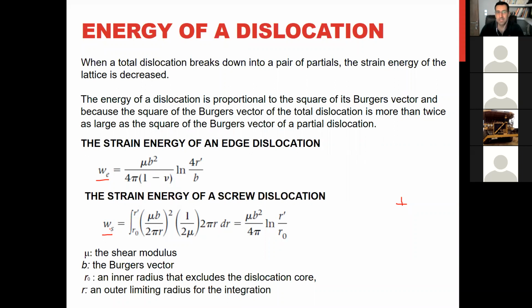I'm not going into details of how we can calculate. You can find it in the reference books I presented. So you can see the details, but something very important for us, and easy to use, is that the energy of the dislocation is related to the square of the Burgers vectors. Yeah. So if you calculate the b² for each dislocation, you can relate it with the strain energy of the dislocation.